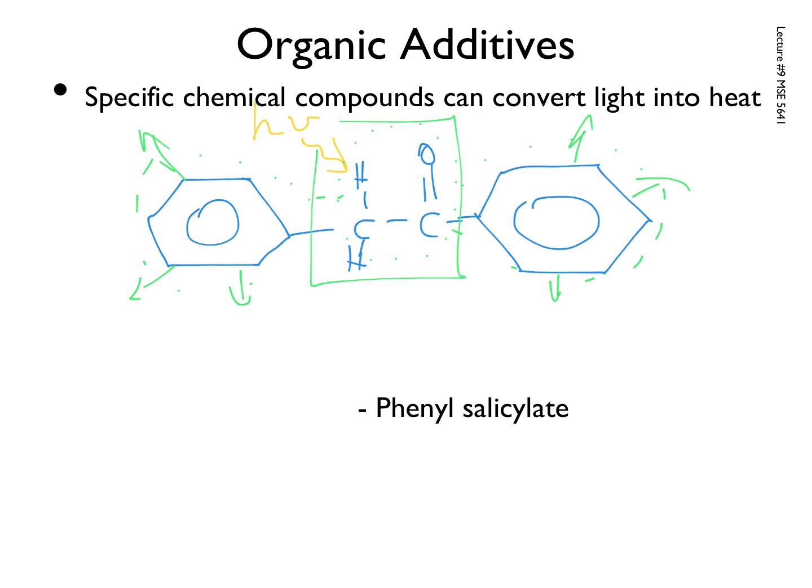They do the same thing. They take one light and convert it into a different wavelength of light. Here we're taking light and converting it into thermal energy. So it starts to vibrate the phenyl salicylate, and eventually that leaves, all right? But in doing so, what it's done is it's shielded the polypropylene from these photons, meaning that it can last longer when this is present versus when it's not present. Okay? So again, one of these invisible additives that makes up all polypropylene that we know of. It's necessary for this particular purpose. It's invisible to you and me, but it's always there.